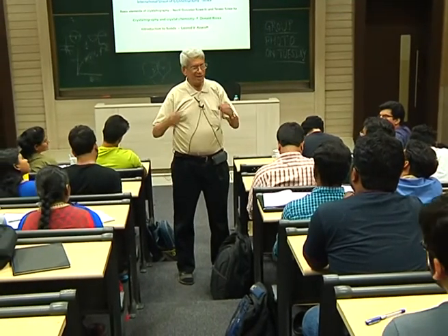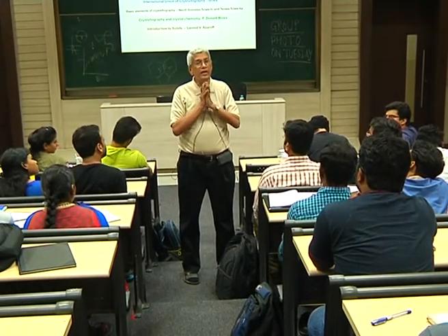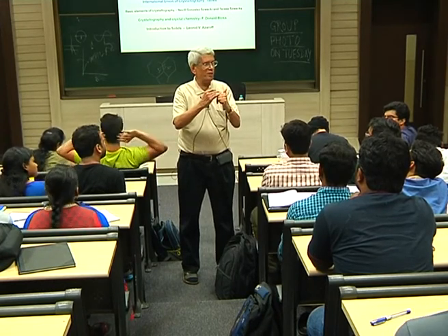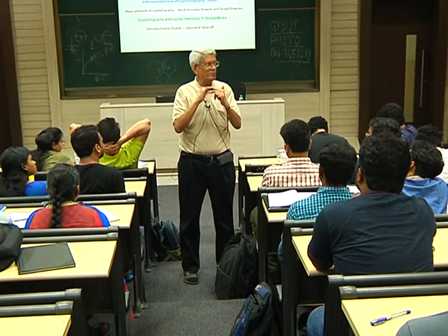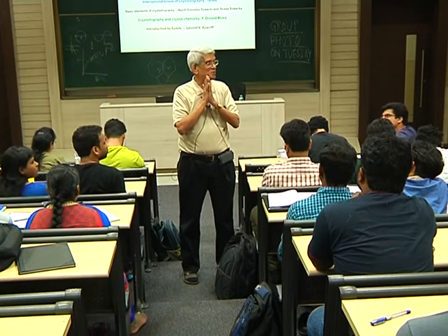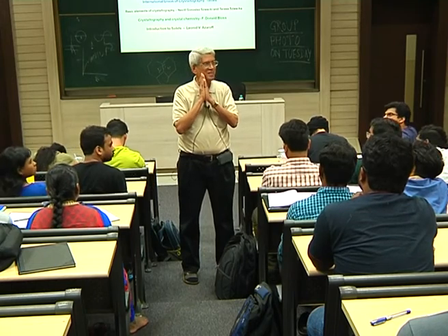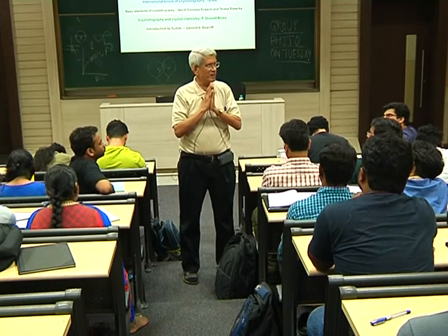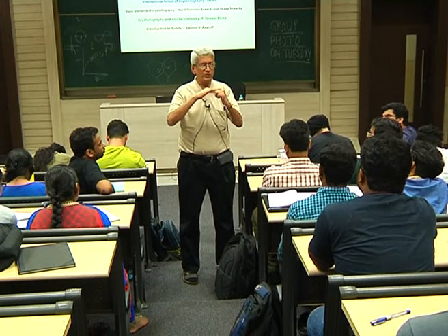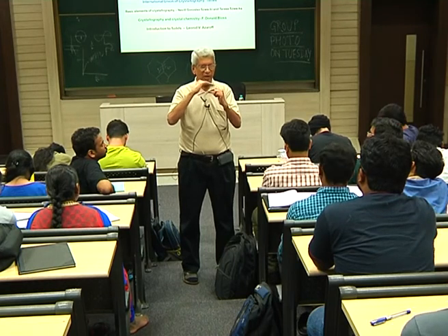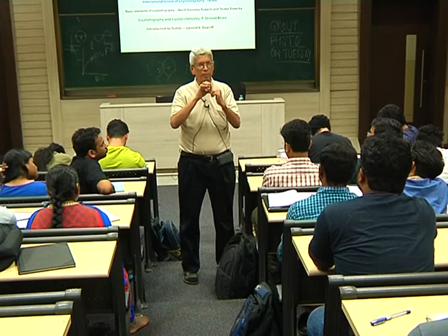Essentially, the earlier theory was telling that this atmosphere forms as the dislocation moves with a particular velocity and the solute also moves and they come and join together. But later, Cottrell is one person who has done a lot of work on looking at this. And the present one is that you have a forest of dislocations. As the glide dislocation moves, they are stopped at the forest of dislocations. During that time, these solutes come and get attached to it.